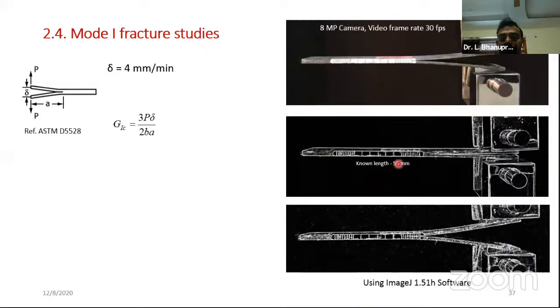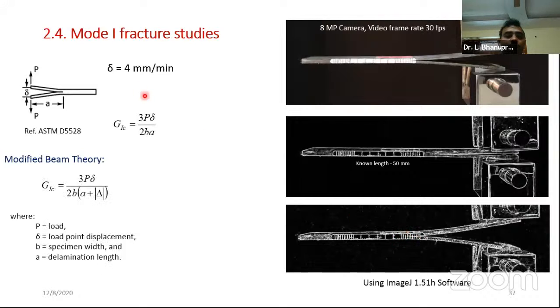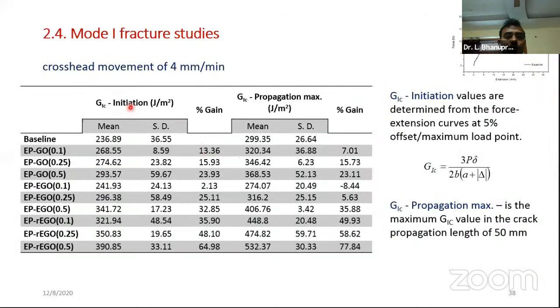We have clearly studied the propagation of the crack using ImageJ software. Each and every frame has been clearly observed for crack propagation, and we have drawn the graph between crack propagation and crack initiation. Both the initiation fracture toughness and propagation fracture toughness have been calculated. And here also we have observed a very good improvement in the properties. At 0.5 we can notice 65% improvement. At 0.25 it is 48% improvement. Propagation is higher still, but in most cases initiation is considered to be the fracture toughness. So that is also very high, as we have observed.